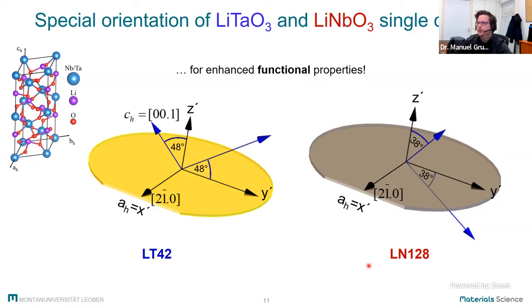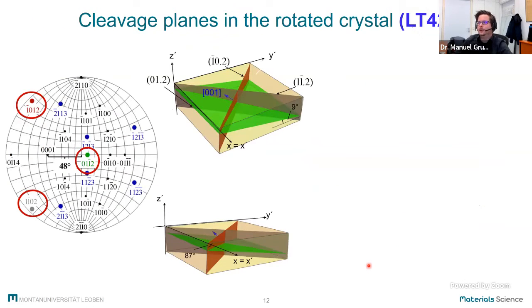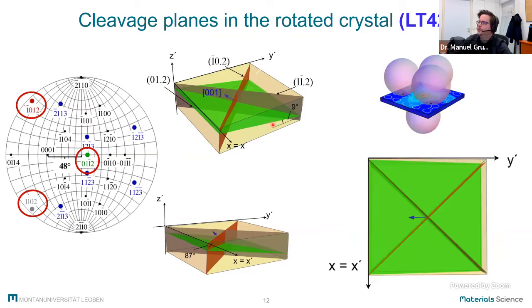So if we now have a look at how the cleavage planes are aligned in our single crystals, we can see that two of those cleavage planes are almost perpendicular to the surface, and one of the planes is almost parallel to the surface. And if we again look at our